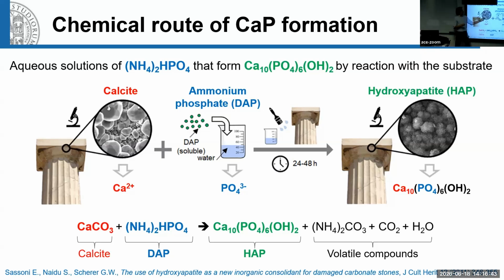So the idea is I buy salt, white crystals, I dissolve them in water, okay, no organic solvent, nothing strange. So I obtain a solution, something transparent with a viscosity similar to that of water, and then I apply it onto the stone by spraying, brushing, by applying a poultice and so on. And then in a matter of a few hours, one day on average, we have a chemical reaction between the calcium ions from the substrate and the phosphate ions that we provide, and we form new calcium phosphate minerals.